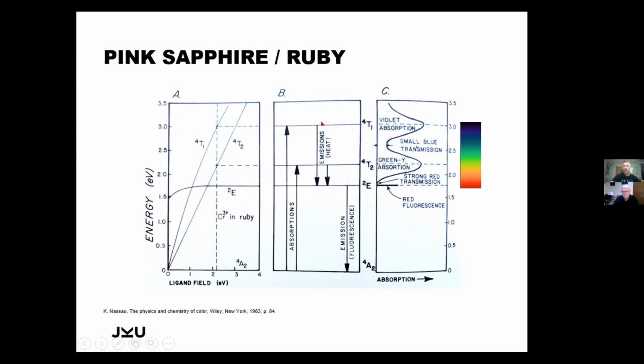What I just want to mention here briefly and not explain in detail is the fluorescence, because what happens to the electrons once they're excited is that they cannot stay in the excited level, they have to come back to the ground level. And unfortunately, physics tells us that it's not possible to fall down the same way that they are excited. So they have an intermediate level, which is here the 2E level. By creating some heat, they come down to this E level, and from this E level it's now allowed to go down to the ground level just very slowly, and this slow emission of color in this case is what we see as fluorescence.